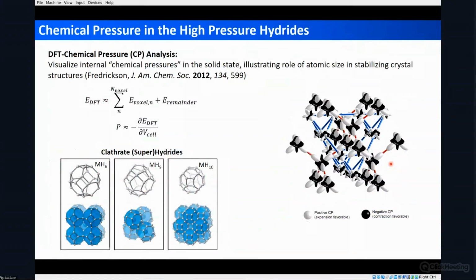So one of the things that we wanted to look at is the chemical pressure. This is a method that was introduced by Danny Fredrickson. It talks about if you have an atom with a particular ionic radius, or just radius in general, what kind of local pressures are induced by that element within the crystalline lattice. And how you calculate chemical pressure is by doing a slight expansion or a slight contraction in your DFT calculation, and then calculating the pressure defined as dE over dV, and doing so on each voxel within the calculation. And then the chemical pressure maps can be mapped onto these types of spherical harmonics.